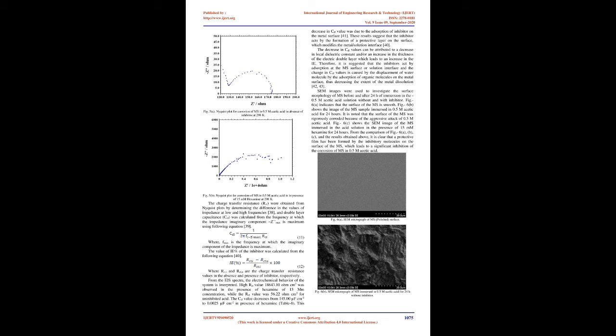Generally, a magnitude of ΔG°ads around -20 kJ/mol or less negative can be assumed to be due to an electrostatic interaction between the charged molecule of the inhibitor and the charged metal surface, i.e. physisorption 27, 28. If the value of standard free energy of adsorption, ΔG°ads, is around -40 kJ/mol or